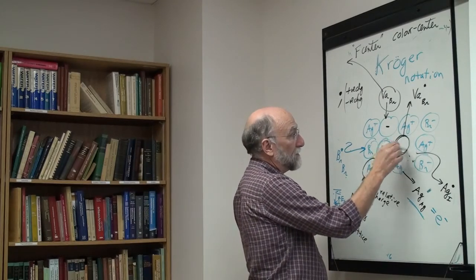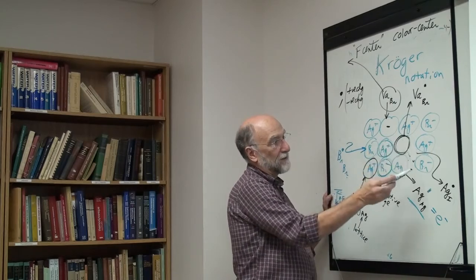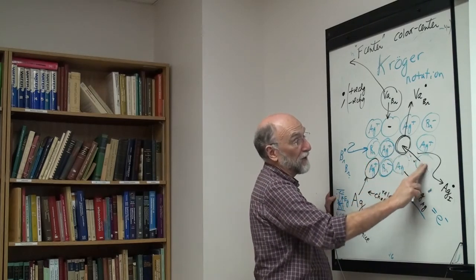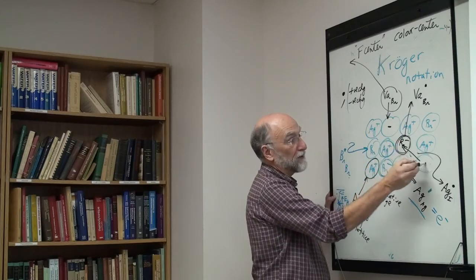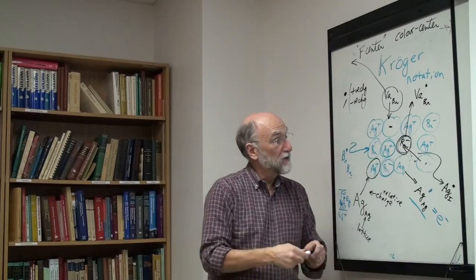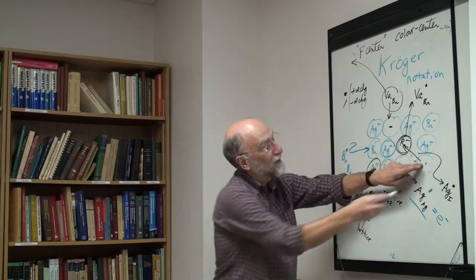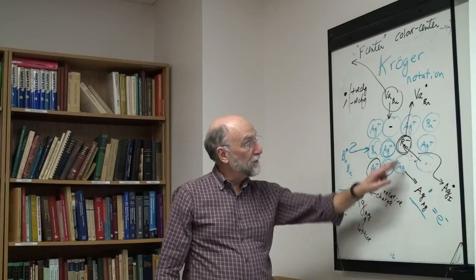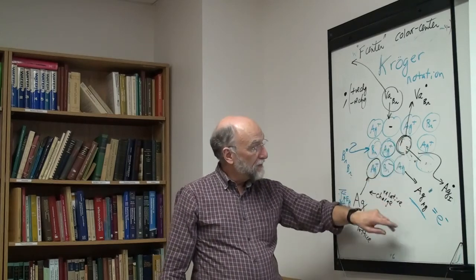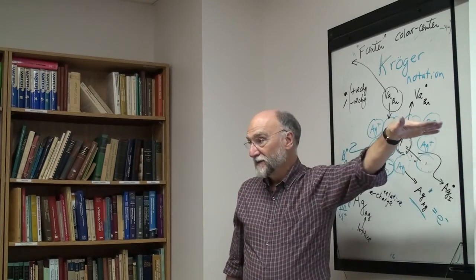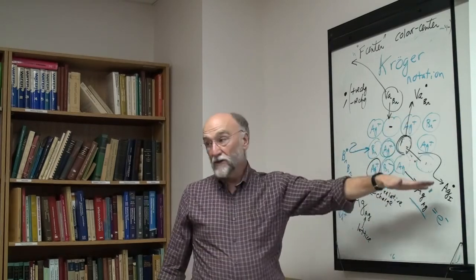If you have a bromine vacancy, then this bromine can hop into here. This is actual transport of the nucleus. This bromine hops over here, now the vacancy has moved here. You say the vacancy moves, but really it's the atoms hopping: this thing hops, and then another thing hops in, so the vacancy is moving along, but that's a transport. If the vacancy is a bromine vacancy, it has a net positive charge, so that's a transfer of positive ionic charge that way. Also, diffusion occurs that way.